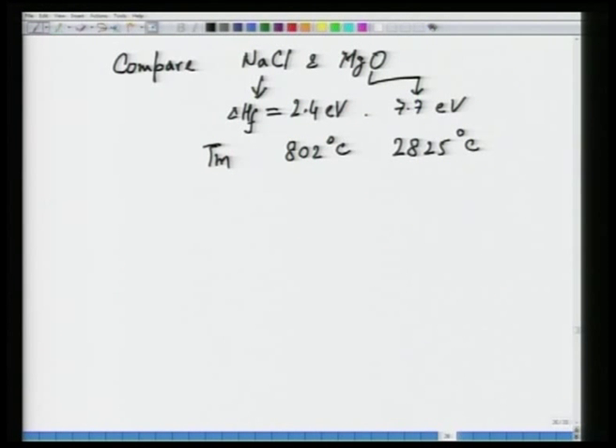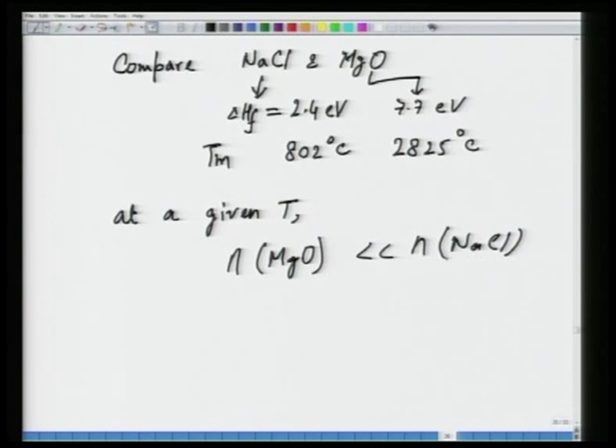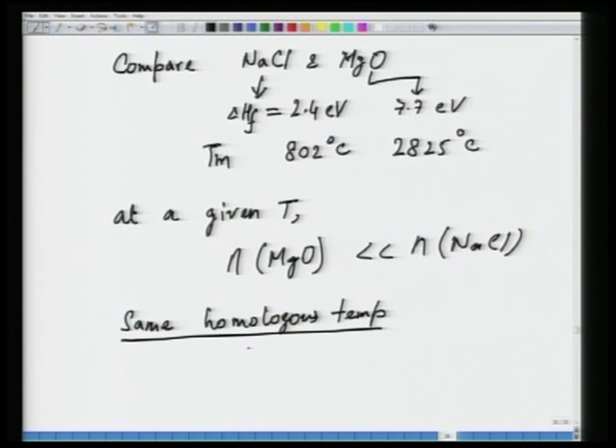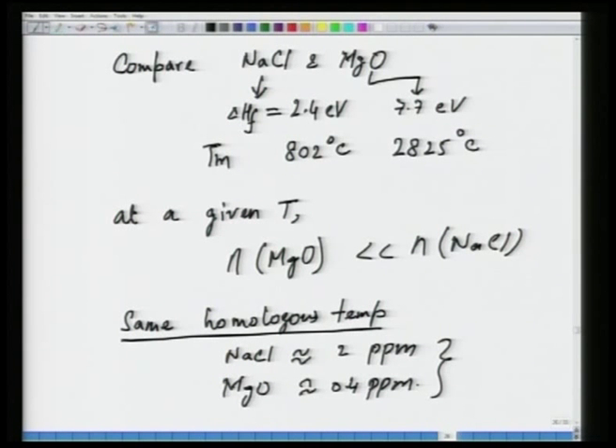enthalpy of defect formation. So, as a result, at a given temperature, the number of defects in MgO is much smaller than in NaCl, and this is because of higher defect formation energy in MgO as a result of higher bond energy. However, if we scale it to the same homologous temperature, then defect concentrations can be almost comparable. So, at the same homologous temperature, of course below the melting point of NaCl, you can find that NaCl will have roughly 2 ppm defects and MgO will have approximately 0.4 ppm. So, they are more comparable when you talk about the same homologous temperature, but the point here is the effect of bond energies and the temperature.